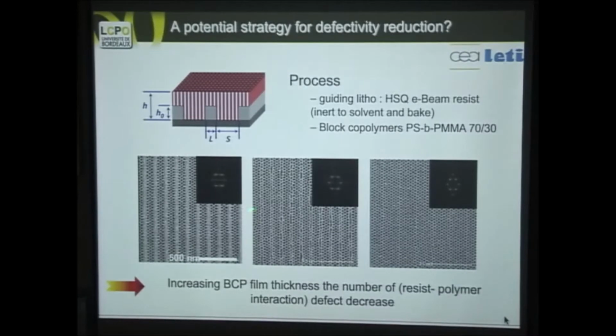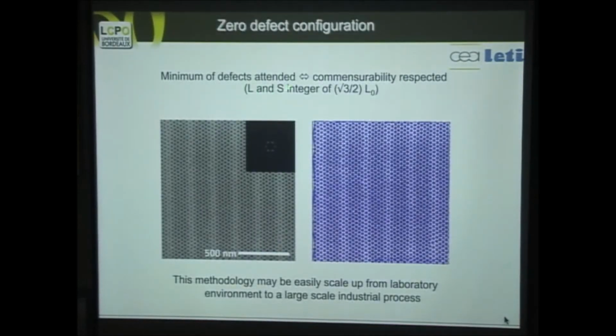So in the studies we've done recently, we did a systematic study. Here you see the resins, the photoresist, and you see the block copolymers, and you have the pitch of this system, and you have the periodicity of the copolymer. When we adjust and have really well-defined periodicity of the copolymer and periodicity of the resin, we can see that slowly, and also when we increase the thickness of the resin that goes just on the surface, and we have some theory to explain all of this, the defects that eventually will be on the ridge inside here on the bottom are slowly relieved and can be annealed out by themselves. The rule will be that L plus S has to be an integer of the square root of 3 over 2 of the length. This L is the periodicity of the block copolymer.